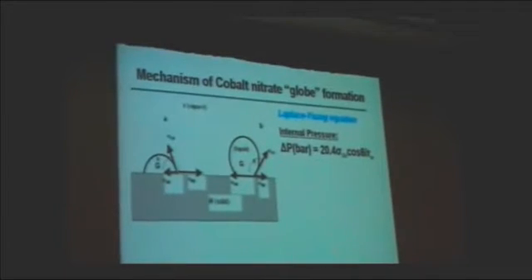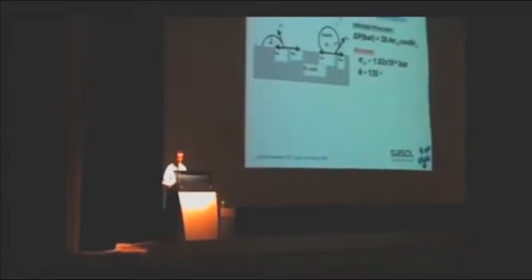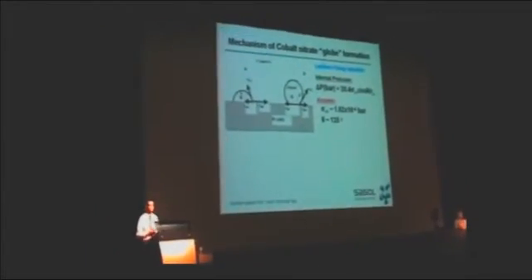In both cases, you can define this wetting angle theta. And by making use of the Laplace-Young equation, if you know the surface tension of this droplet, and you know the wetting angle, as well as the radius of the meniscus of this droplet, you can actually calculate the internal pressure in this droplet. We simply don't have all of these values, so we had to make use of a couple of assumptions.